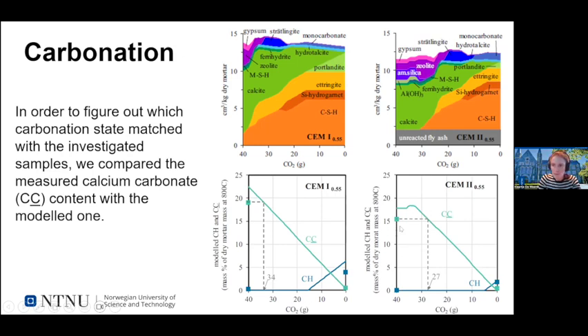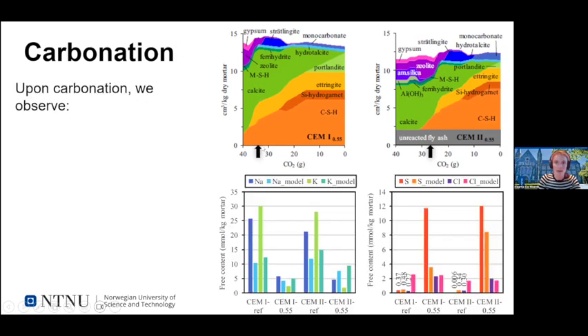And we did the same for our fly ash cement. We had less calcium carbonate there, and there we had an equivalent CO2 level of about 27. So in these graphs, we're approximately here in this phase assemblage. Then we extracted the pore solution composition at this phase assemblage, and we compared it with some experimental results.